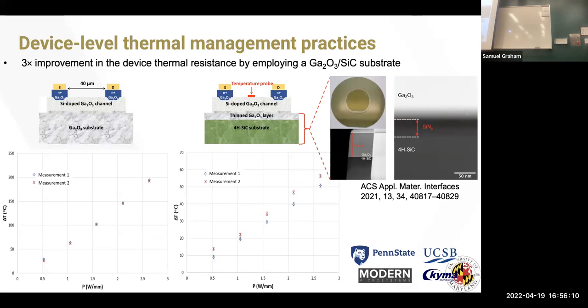No, seriously, what you do is you typically use Raman thermometry. And so the way we've been doing this, when you have ultra-wide bandgap materials, you use invisible light, it wants to go straight through, and you don't really know what you're measuring. So we typically put a material on top, a nanoparticle or a series of nanoparticles that are Raman active. So when I receive that Raman signature, I know it's coming from the top of the device. We'll use a sort of dielectric, you can even use diamond particles on top. And so that's how we do it. We do Raman spectroscopy on the top of the device. So he's measuring somewhere here in the middle of this channel, but the particles are sitting on top.